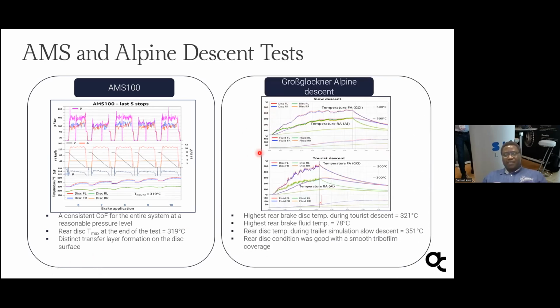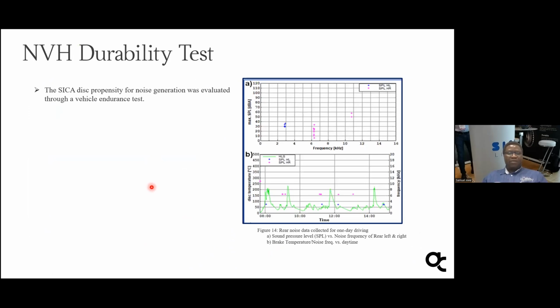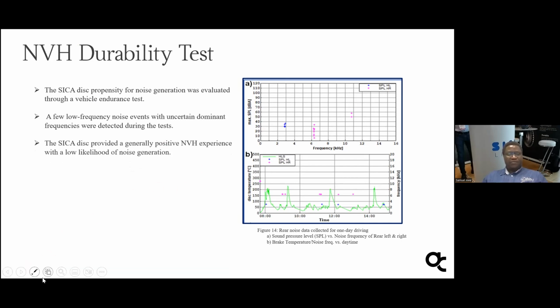Then for the downhill descent, similar behavior was observed, with a good brake fluid temperature at the end of the braking event, around 78, which is far, far lower than the boiling temperature of the brake fluid, which is around 180 degrees. So, which is good. Then we also evaluated the durability, NVH. From this we investigate the propensity to produce noise, and the results indicated good behavior at the end, as you can see from here.